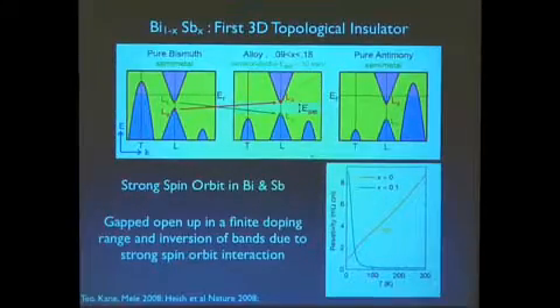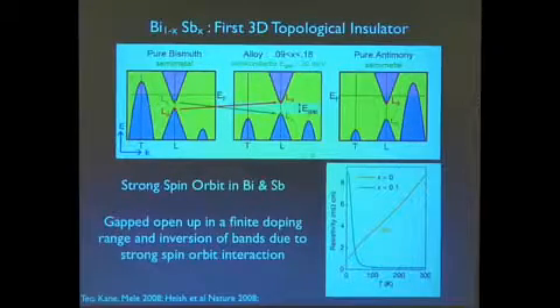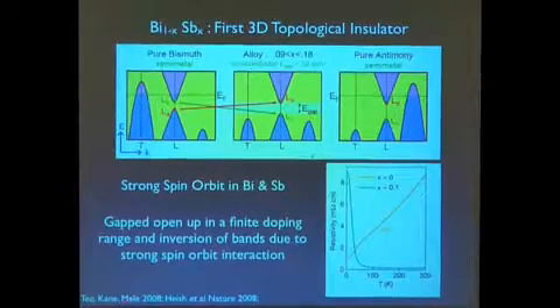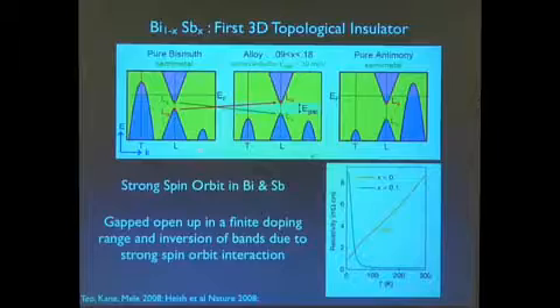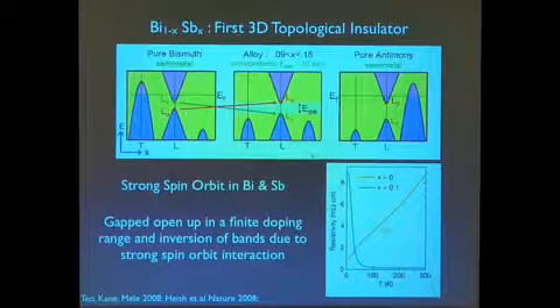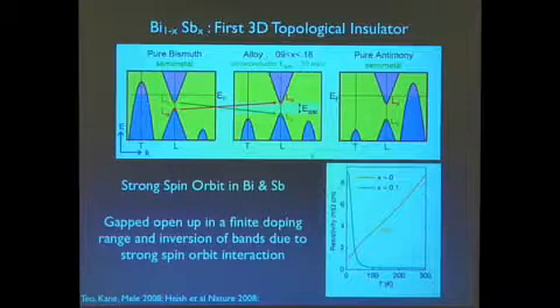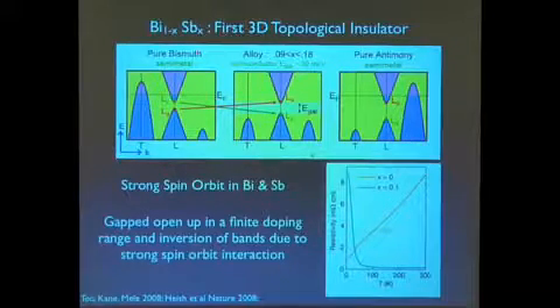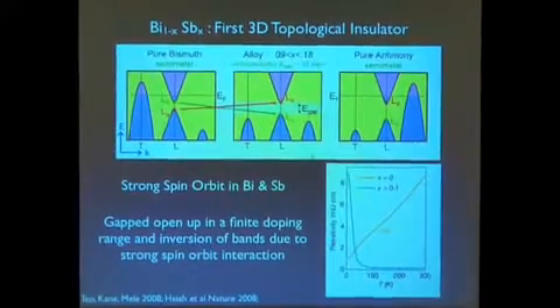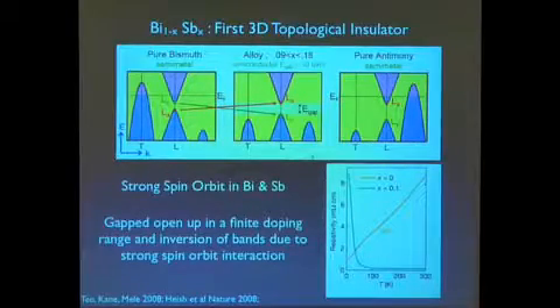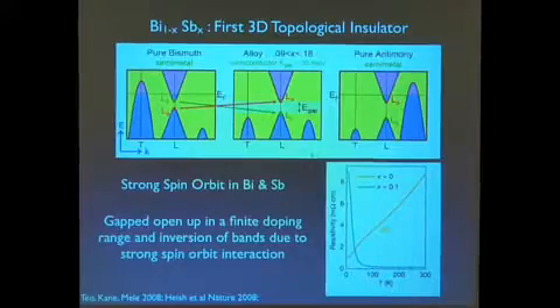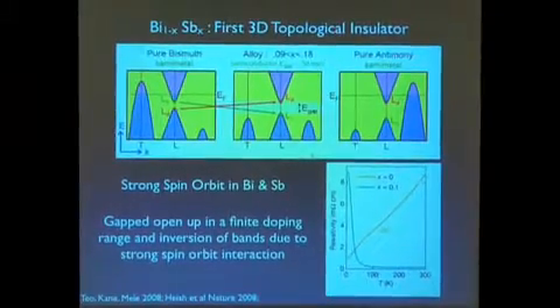OK, so what about looking at a topological insulator? So I'm going to show you an experiment on bismuth antimony first. This is a compound that, remember, you need a band inversion to create a topological insulator. So Charles Kane and Gene Mele and their co-workers realized that if you look at bismuth and antimony, they actually have this band inversion that I spoke about for you already happening. Just Mother Nature gives that to you by turning on spin-orbit coupling. And basically proposed the idea of making an alloy. And this alloy basically has the benefit that you can tune the chemical potential and put it in the middle of this inverted band structure, in the middle of this gap, making you a topological insulator, which was first done by Bob Cava at Princeton.